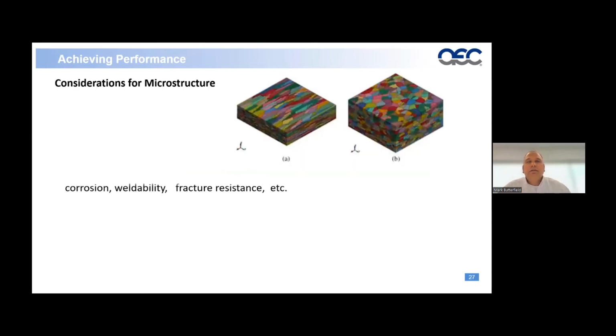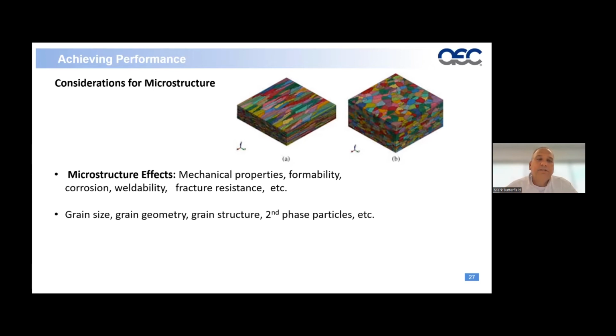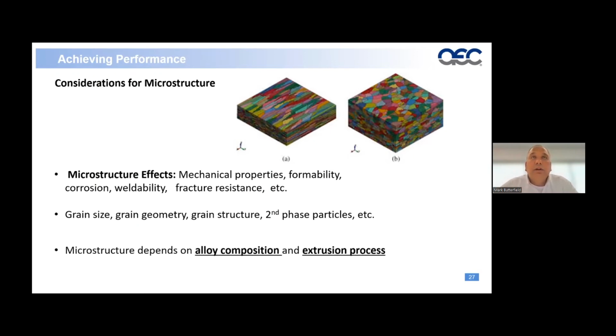So, considerations for microstructure. Microstructure affects mechanical properties, formability, corrosion, weldability, and fracture resistance. When we think about today's applications, those are the first things we're thinking about, especially with some of these complex structures that are being extruded today. Grain size, grain geometry, structure, second phase particles, etc. And microstructure depends on alloy composition and the extrusion process utilized to produce it. As we talked about earlier, not only is it the alloy, but just as importantly, it's the process in which the product is produced that becomes most critical.